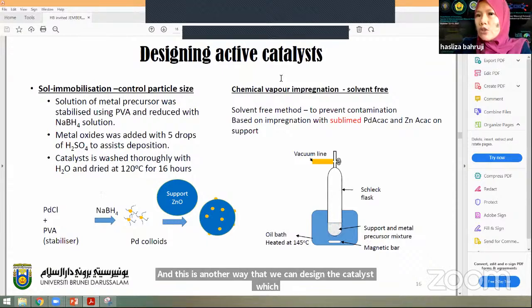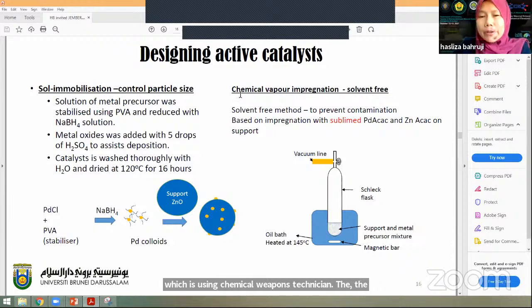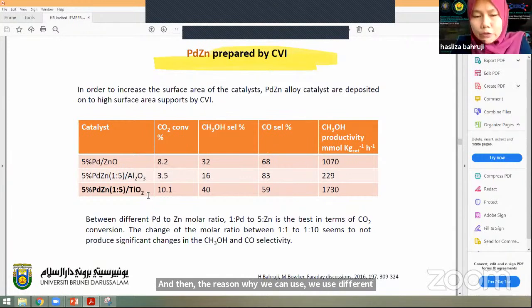And this is another way that we can design the catalyst, which is using chemical vapor impregnation. The benefit of this method is it gives us a solvent-free method that can create palladium zinc alloy. We also managed to produce palladium zinc alloy on titania, alumina, and different types of support, and we can increase the activity when we add them on titania. The reason why we use different types of support apart from zinc oxide is that, as we showed from XPS, there is always segregation of zinc oxide to create this palladium zinc alloy. So when we produce palladium zinc alloy on titania, we stop the tendency of zinc oxide as a support to keep donating zinc to produce zinc alloy, and this will restrict the enlargement or the growth of palladium zinc alloy.